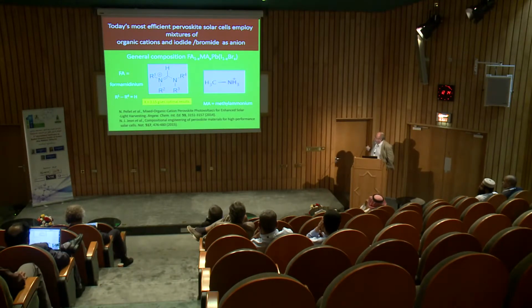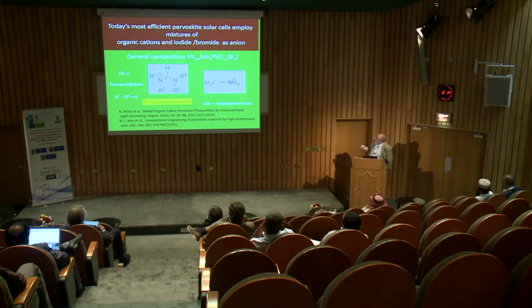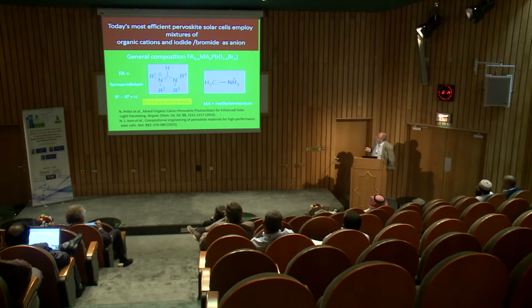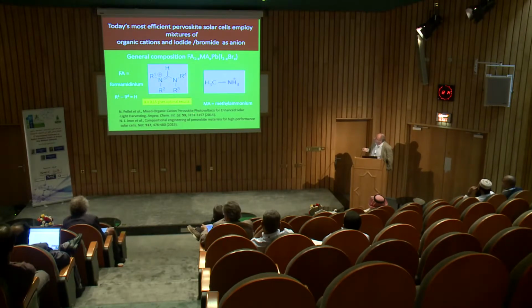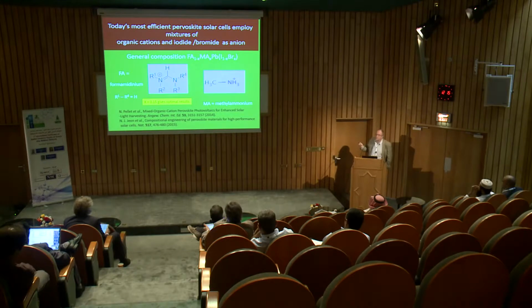The best results, and I will now not go through so much more, to focus on our own recent results. Our best results at EPFL at the moment is based on a mixed perovskite. The classical one is methylammonium lead triiodide, but here you see we start to mix in some bromide. It's tuning the band gap a little bit, and I think also makes the halide a bit more stable. We have lead, and then we mix the organic part, which is methylammonium, and the formamidinium cation is also mixed to tune the gap a little bit, and also to optimize the morphology of the perovskite. So this was presented from the EPFL group in Angewandte, and Professor Seok from Korea has then the certified world record of 20.1% using this kind of mixed perovskite.